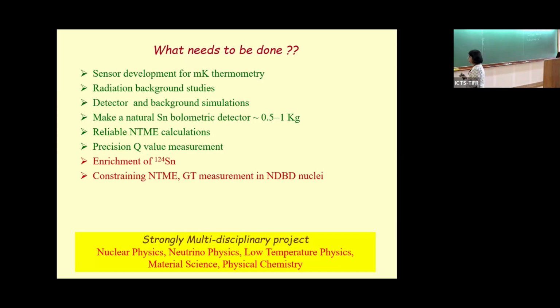5% is not a good abundance for a large scale detector, because we are looking at 124 tin. But tin is one of the nuclei which has many isotopes. It has 112, 116, 120 and so on. And all even isotopes have a probability of double beta decay, either beta minus or beta plus. If you look at the nuclear binding energies, it will be clear: the most neutron rich will have the highest Q value, and as you go down, it will lower. So when you have 120 and 124 tin, 120 tin will form the background on the lower side of 124 tin. So I will be able to look at NDBD of 124 tin cleanly, even if these are present.